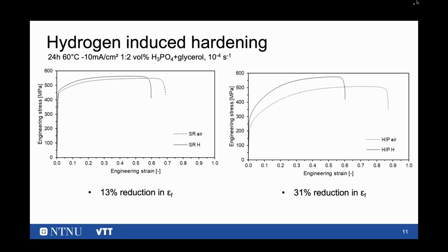Although I should note the absolute value is around 0.6 engineering strain where it fails. Apart from this embrittlement effect, we also see a hydrogen-induced hardening. Very low for the stress relief condition, but quite significant for the hot isostatic pressed condition. So we looked further: where does this come from?